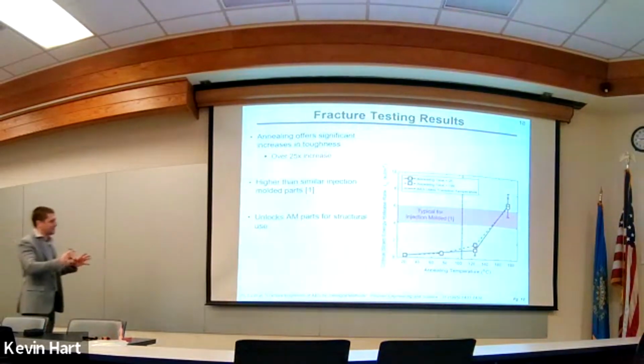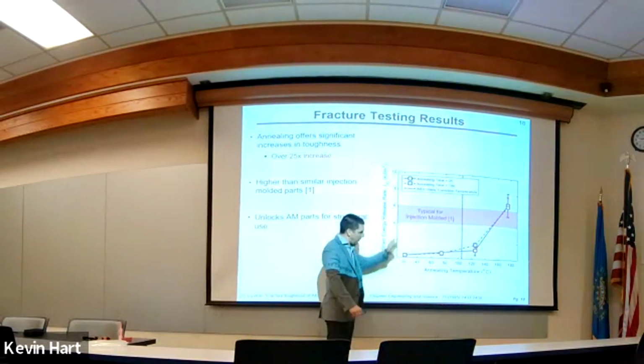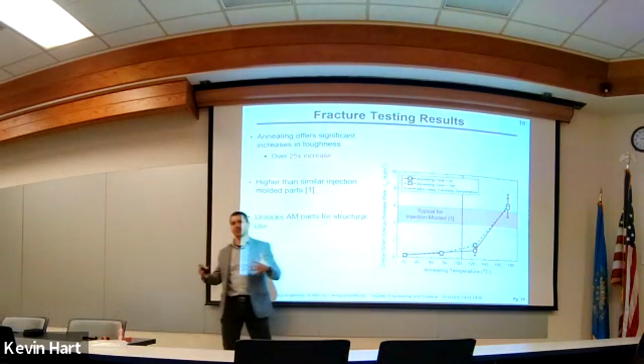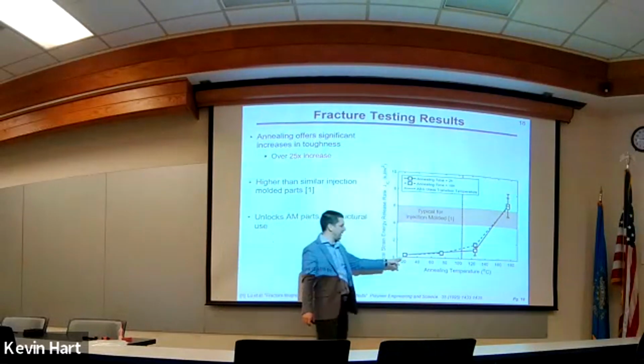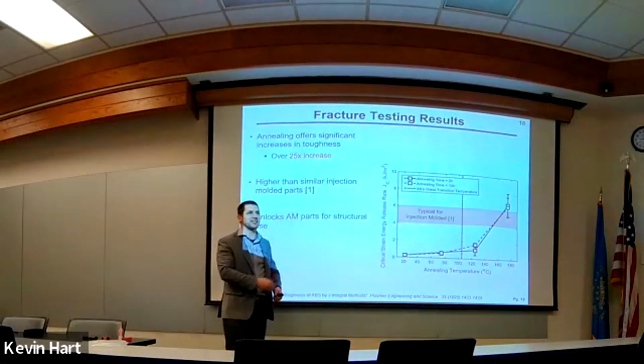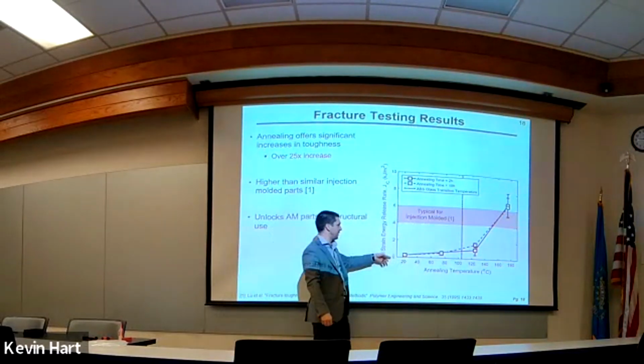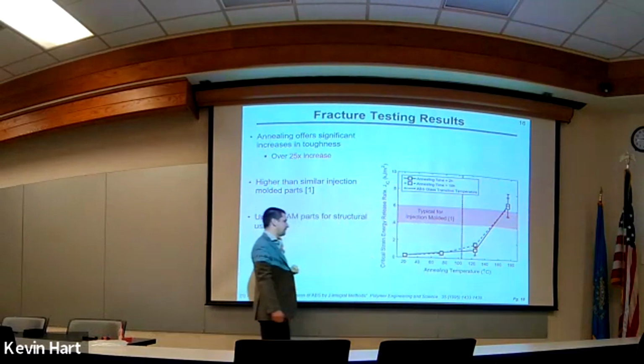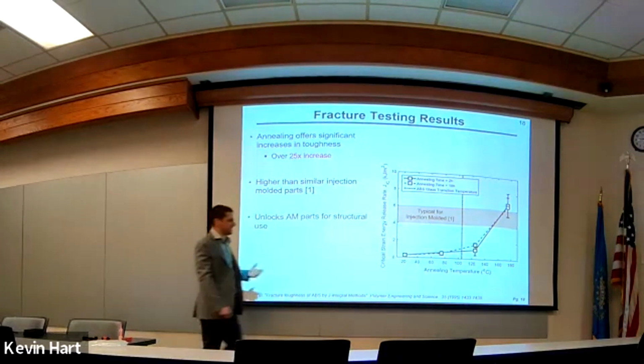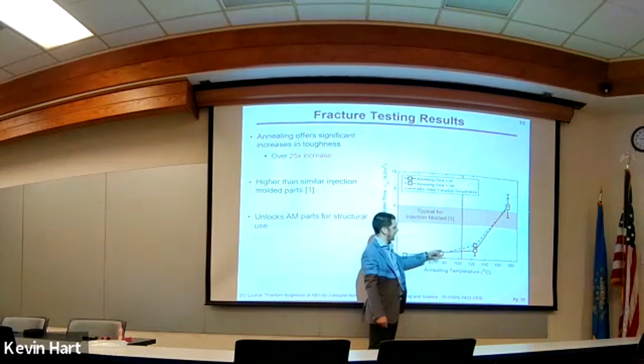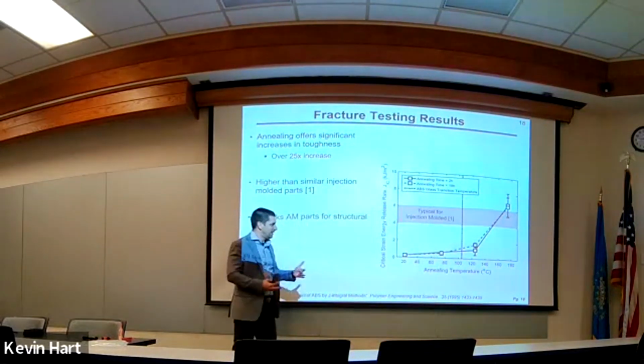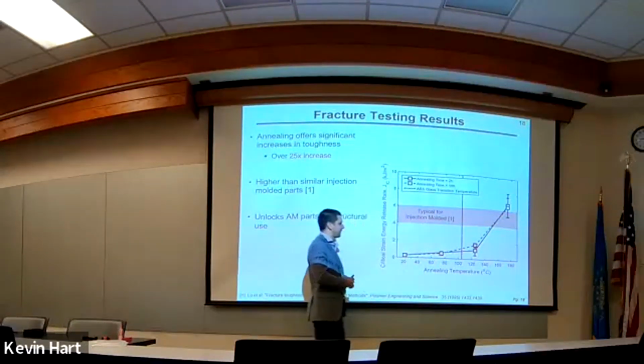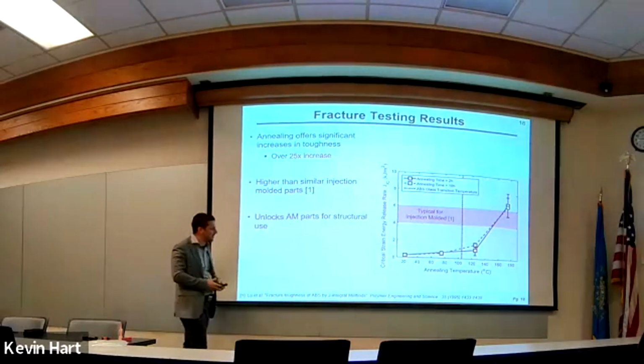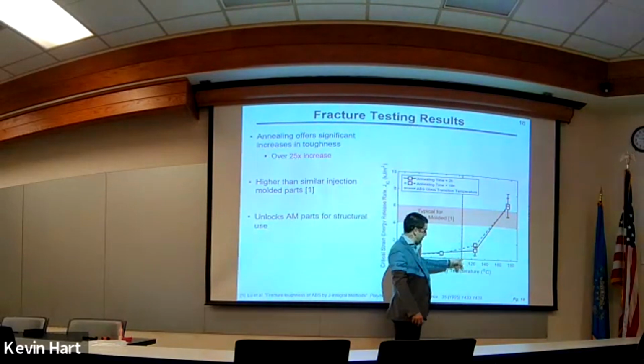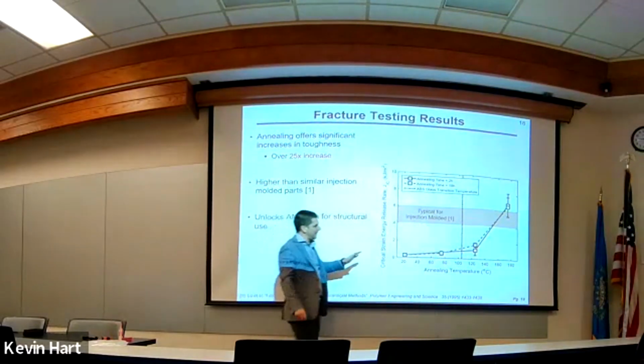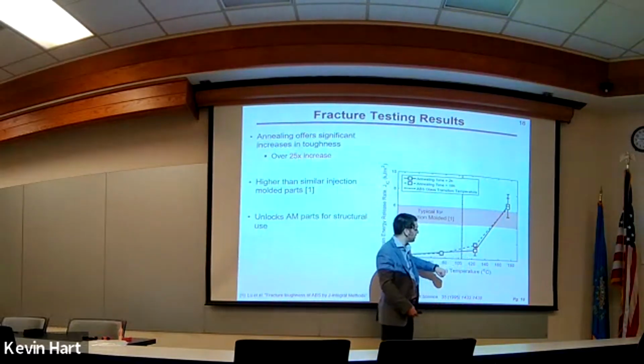So we picked a bunch of annealing times and temperatures that were selected intelligently, and let's see what we get. So here's the rub. This is the data that comes from that simple test. Here we have annealing temperature on the x-axis, and on the y-axis your interlayer toughness, your critical strain energy release rate. If you test the sample at room temperature, which is basically you 3D printed it and then tested it, we know that toughness is very low, about 250 joules per meter squared. Very low toughness. If you then anneal this at 75 C, let's say, for 2 or 18 hours, those are the 2 different lines that you see here, you get a little bit of benefit. If you anneal at 75 degrees, you can maybe go up to about 500 joules per meter squared. You're getting some sort of interaction between the layers at that point, but not a ton. But if you start to increase your annealing temperature beyond the glass transition temperature of ABS, then you start to see some melting of the layers into each other, more or less. You start to see some increases in the toughness.